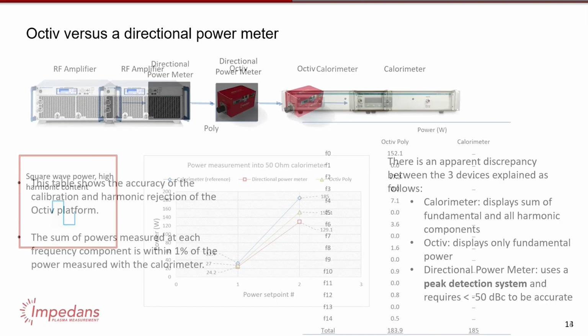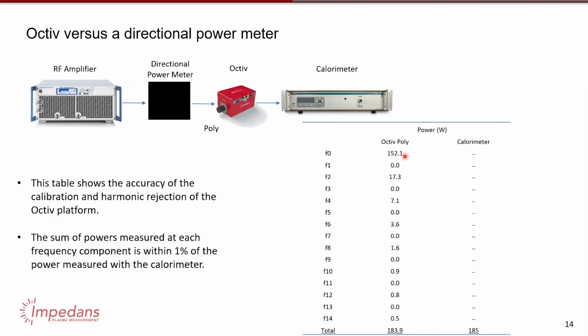And just to note that when you actually add up all of the harmonic content, so if you add up the powers in all the different harmonics, it actually comes very, very close to the calorimeter. And this is considering this is only 15 harmonics. There's quite a lot more in the square wave. There's an infinite amount.